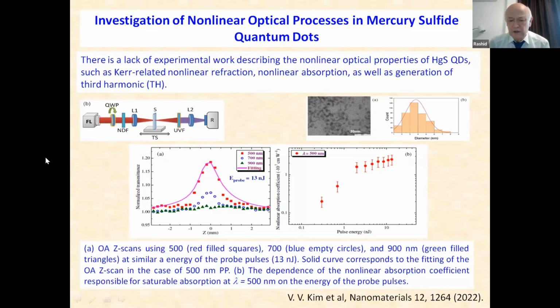You can imagine we use very thin films of those quantum dots, and just showed that the efficiency of third harmonic generation is quite strong, in the range of 10 to the minus 4, while the thickness of those nanoparticle films is in the range of a few hundred nanometers. And those nanoparticles also have small sizes in the range of 3 to 4 nanometers, and the spectral dependence and intensity dependence were analyzed during our studies, which can be useful for the practical applications of those films.